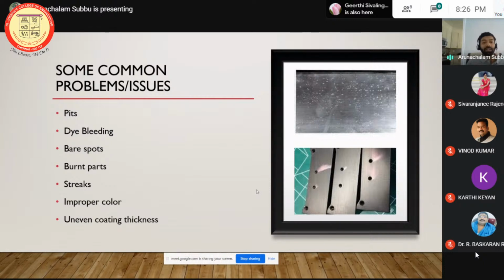And also you see dye bleeding. The bleeding, you can see from the holes to the structure. That is the dye bleeding. That happens if the rinsing is not proper, and if the solution gets into the holes or the small crevices that you see, and if it doesn't come out until the dye tank, the dye starts to bleed. And bare spots are typically kind of like pits, where there won't be any coating. So that also happens. And burnt parts. When you try to apply more electric current, some parts would be burnt, and you cannot use them at all. So that happens. And streaks is also like the dye bleeding.